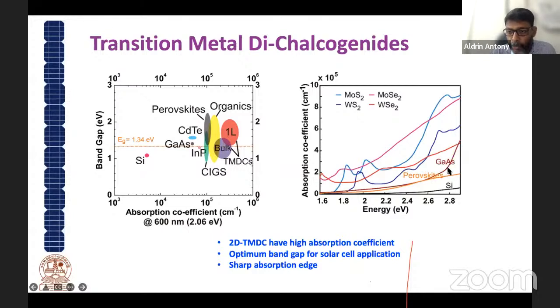It's a very sharp absorption. And if you look into the tungsten selenide, it is weakly absorbing. But if you look into this molybdenum sulfide or tungsten sulfide, you could see very sharp absorption peaks, just like gallium arsenide, having a direct band gap. And this gives a huge potential for applying it as a solar cell, and also in photodetectors, because of these very good sharp absorption edges.